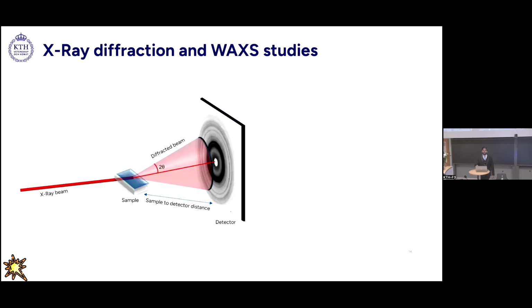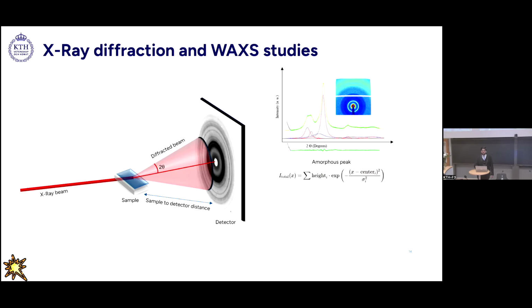In order to see how the material is changing, we tried to do X-ray diffraction and WAXS measurements. Basically, we have a material which we bombard with X-rays, and the diffracted beam is collected at the detector, and after post-processing, we deconvolute different peaks. It's a very standard procedure, and we use some standardized equations to calculate crystallinity as well as the crystallite size for the 200 peak, which is a major crystalline peak in cellulose.